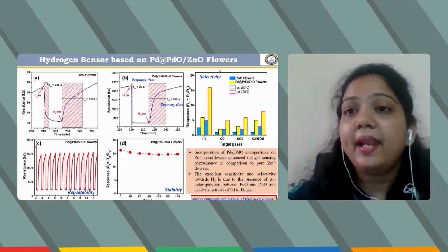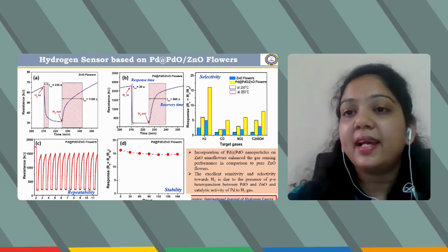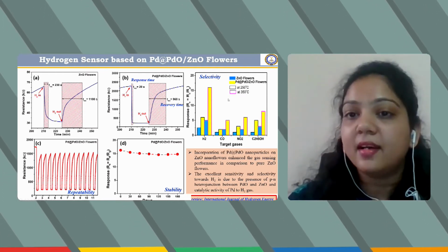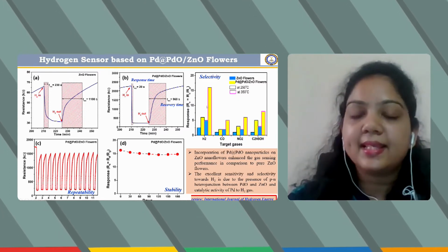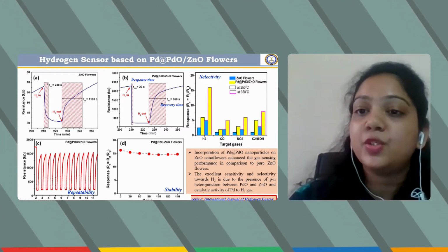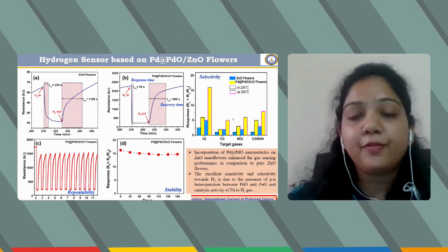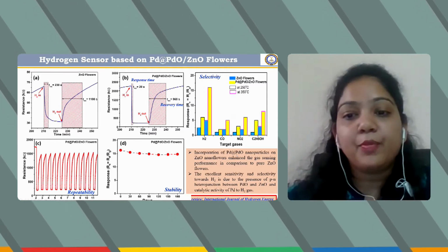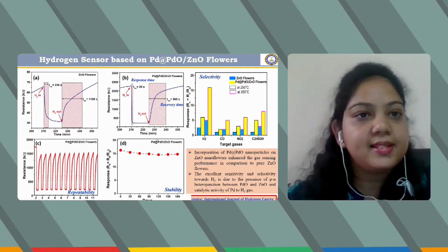In the starting, I talked about some parameters or characteristics of a sensor which are very important. Here you can see that the response time of the PdO flowers is very low, only 20 seconds, and the recovery time is also good. Besides this, we also tested the repeatability and stability of the sensor, which are very important, and the selectivity also. Here you can see that the palladium zinc oxide sensor has a good gas sensing response towards hydrogen in comparison to the other gases, which is very important for a sensor. This work has been communicated and is still awaiting results.